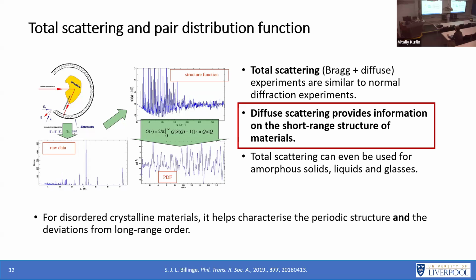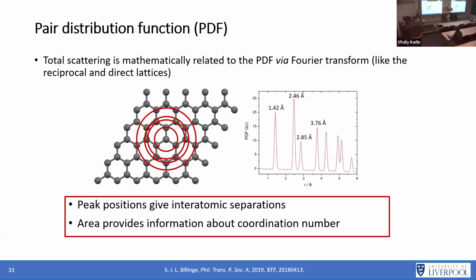However, you can extract data from the diffuse scattering on the short range order of materials, and that's what we need to look at for these disordered systems. You can also do it for ordered systems if you really want to, but it's not going to tell you very much. So we can use this to characterize our amorphous solids, and you can also use it to characterize these disordered crystalline materials as well. Basically, you just do a Fourier transform on your total scattering data, and you end up with what's known as a pair distribution function. I'm not going to go into a whole lot of detail, but just so you've seen it in case it ever comes up again.